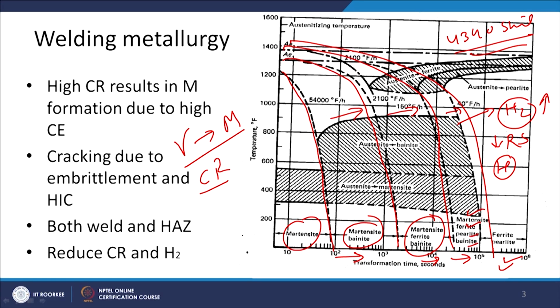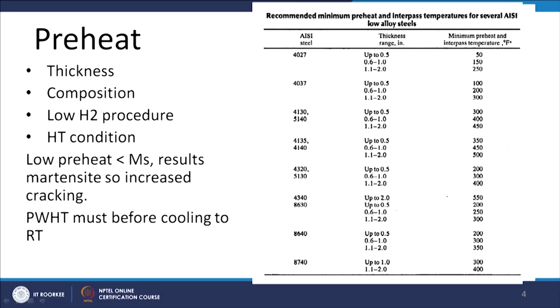So, especially if the martensitic transformation is avoided. It is always good to have suitable cooling rates, so that we can have some soft phase formation in the weld as well as heat affected zone, so that the cracking tendency and the embrittlement tendency of the weld joint can be avoided. As I have said, these are the factors which we need to see while taking decision about the kind of preheat to be used.